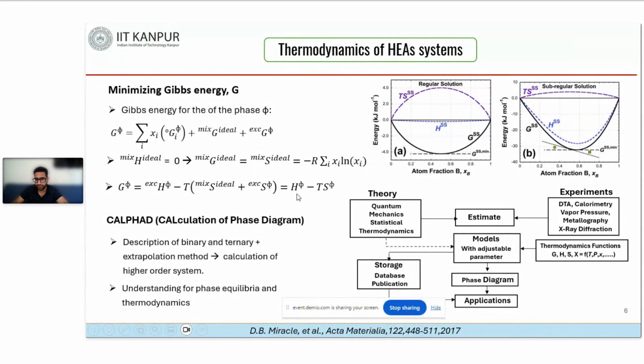the Gibbs free energy of phases, there are different models like the regular solution model and the sub-regular solution model. In the regular solution model, the atoms are considered randomly distributed, and the enthalpy of the solid solution phase, SS meaning solid solution, is not equal to 0 but slightly deviates from this 0 value. The configuration entropy term, the entropy of the solid solution times the temperature, is symmetric about the equiatomic composition. So in the regular solution model, the enthalpy of phases is also symmetric about the equiatomic position.